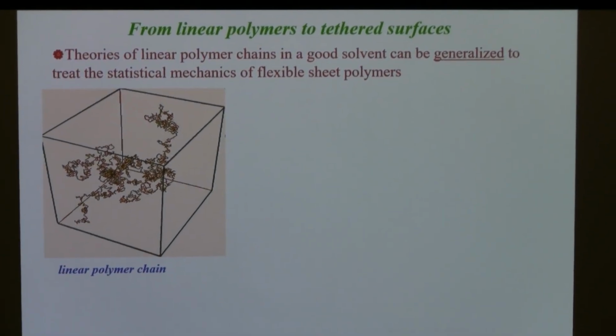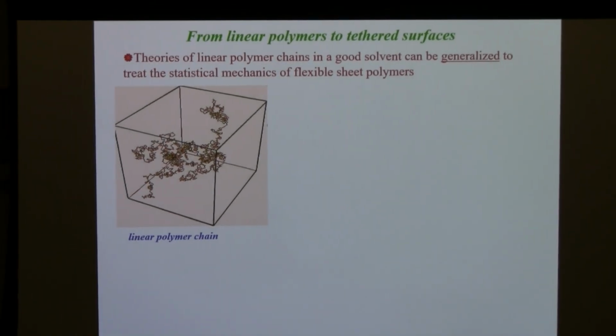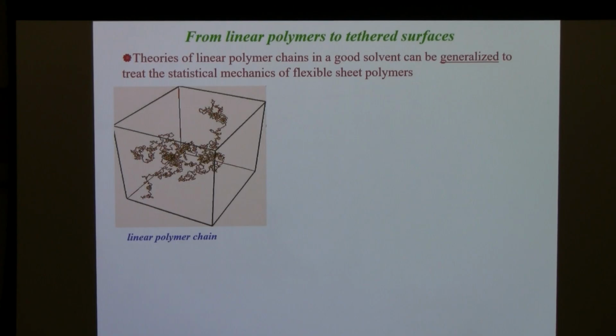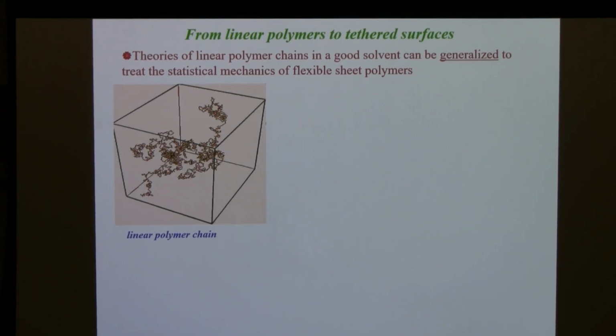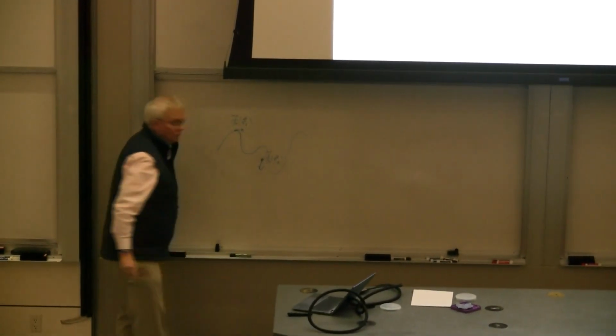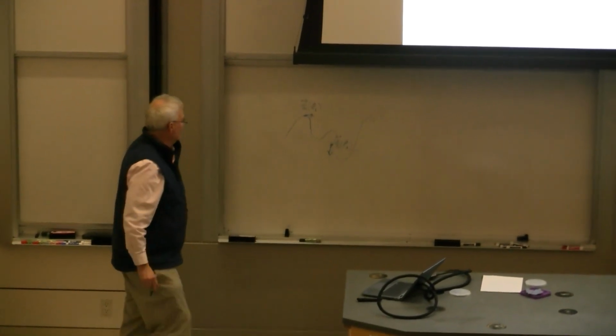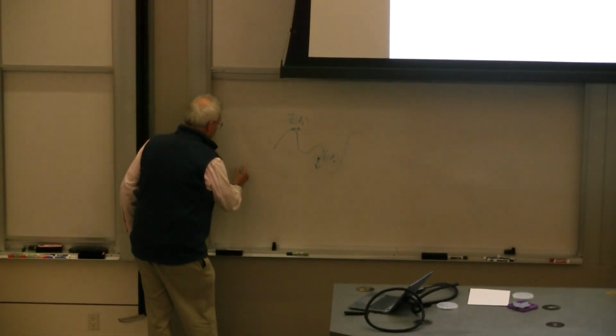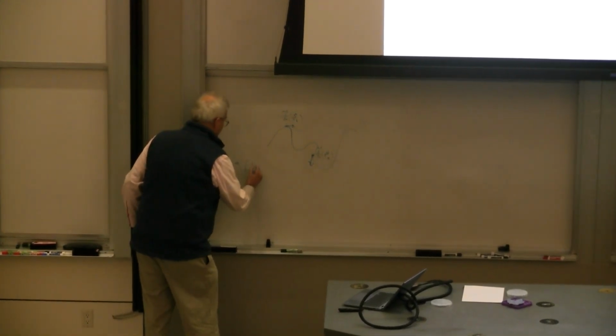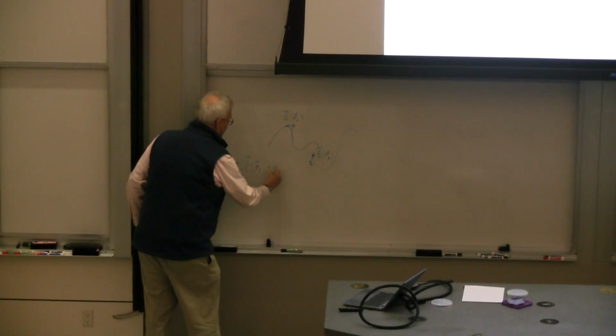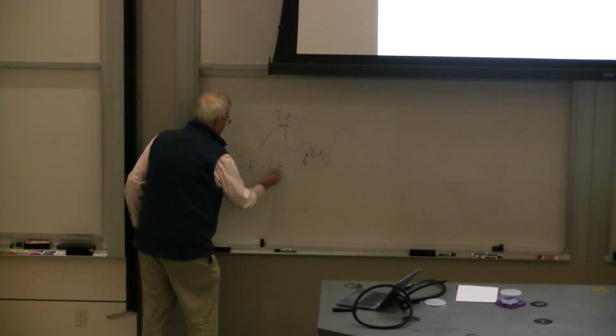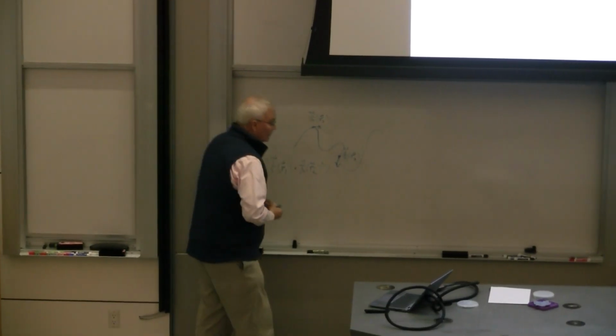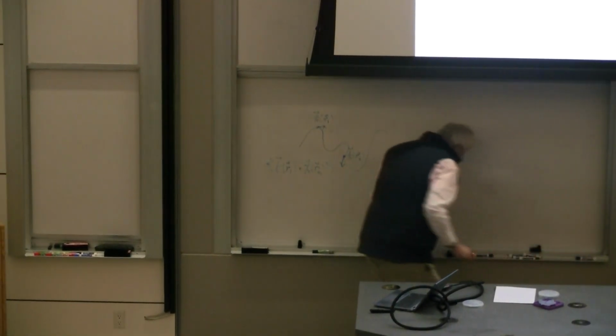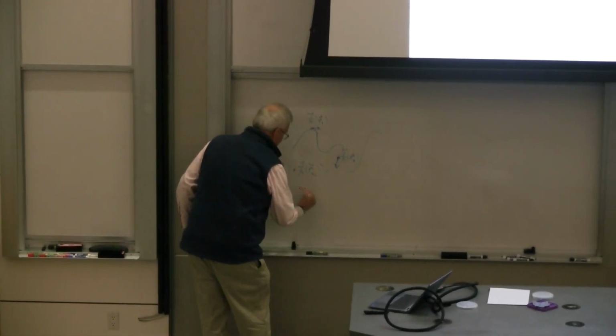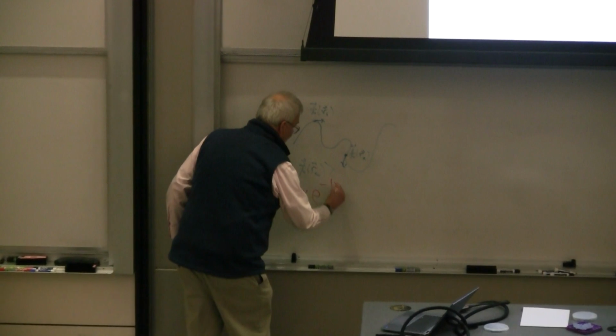And when you have a 2- or 3-dimensional random walk, there's a backbone of the polymer that meanders around. And if I have a local tangent vector here at position R1, and then some other tangent vector down here at position R2, as soon as you start thinking about random walks, it doesn't take long to convince yourself that the correlations between these tangent vectors, T of R1 dotted into T of R2, if we just do some kind of average, this kind of average is going to be falling off, and it typically falls off exponentially fast. So this thing goes like e to the minus how far apart these things are.